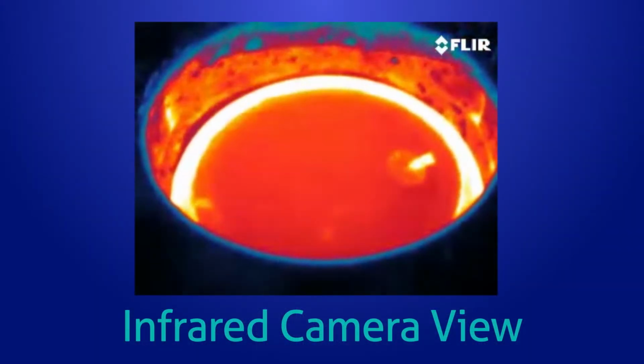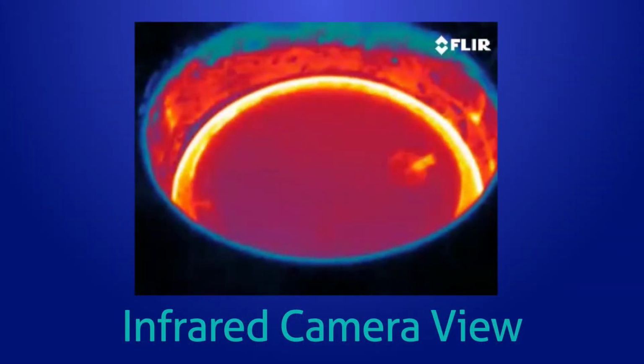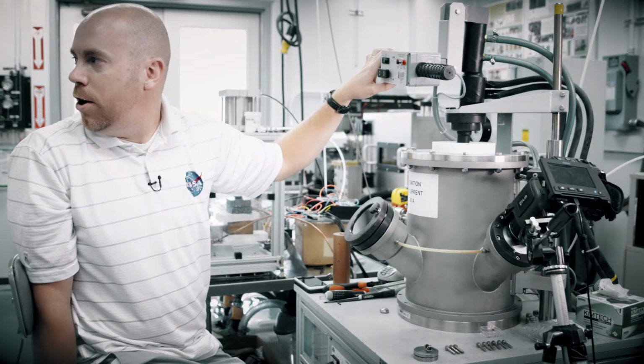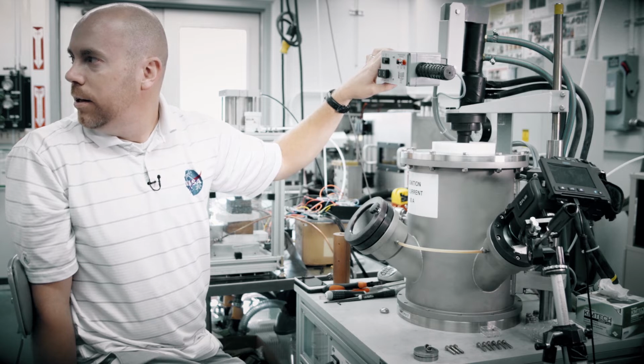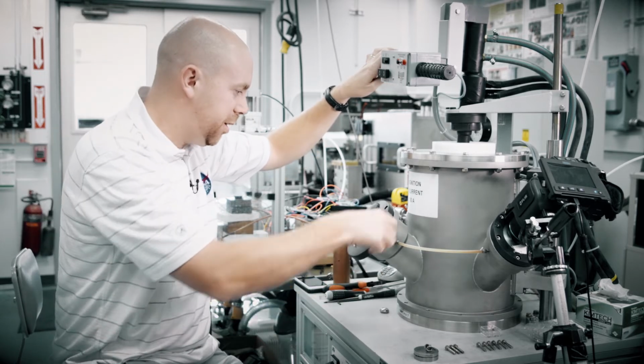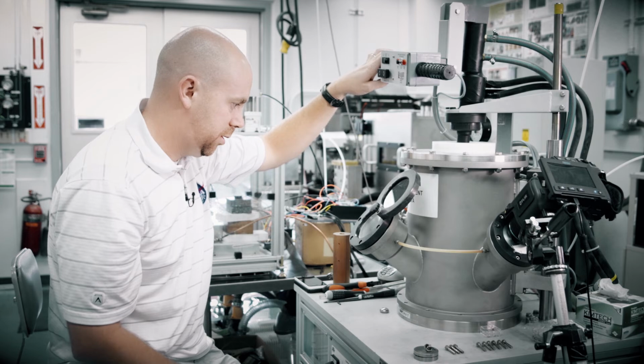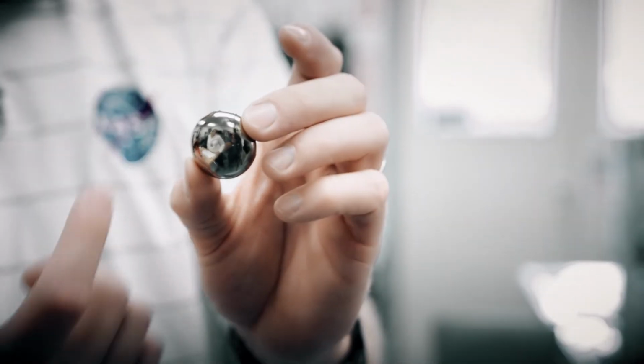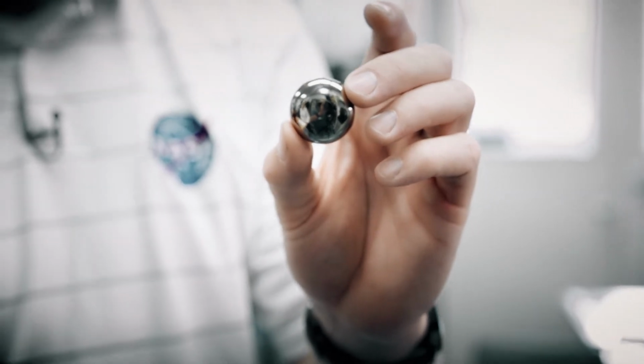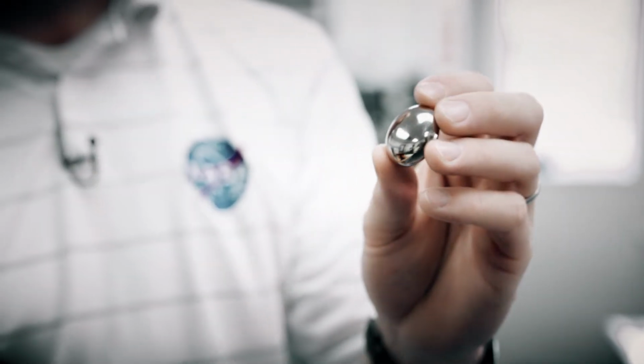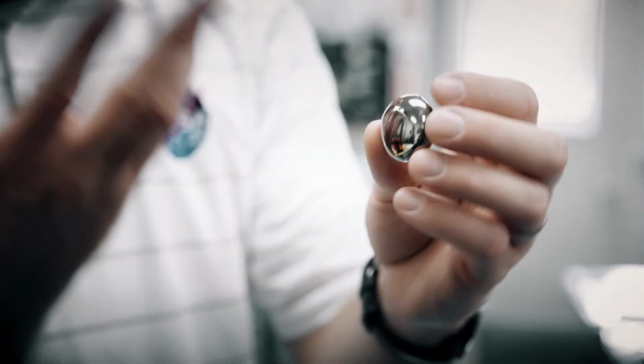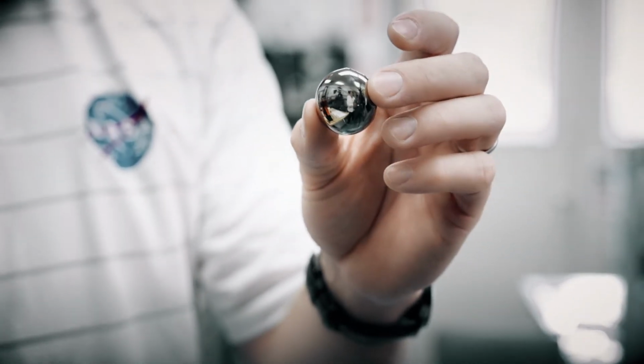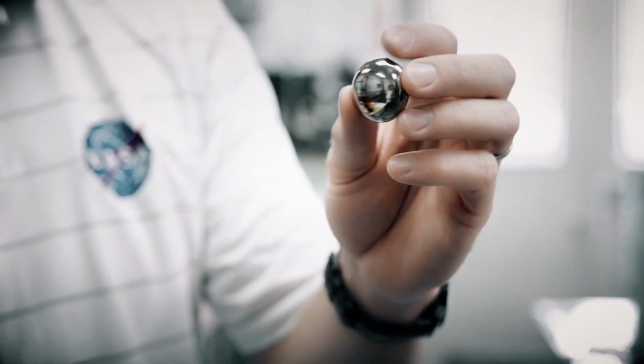So here I'm going to turn off the arc, and we're going to watch the ingot slowly solidify and cool. And we see no crystallization events. So that means that the ingot has frozen into a bulk metallic glass. You can see that the ingot has no trace of crystallization on the surface, has a perfect mirror finish, which is cooled natively. So this is the high surface tension of the metallic glass and no evidence of crystallization.